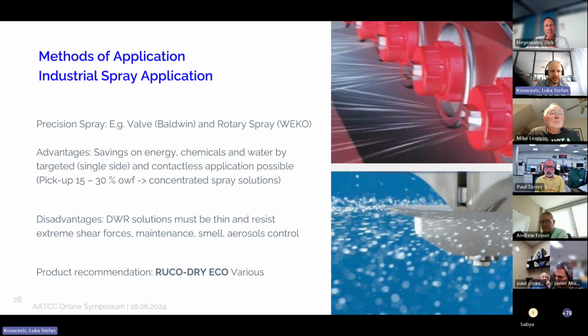So here you only have 15 to 30% pickup of the finishing lacquer compared to 60 to 80, or sometimes 50 to 80, on a regular pad application. So that means your spray solutions have to be a lot more concentrated. That also means you have less water in your spray solution, and in the end you have to evaporate less water from the finish after the finishing. That means you need to apply less energy. At the same time, these systems also create a lot less chemical waste, and what is also charming about this application technique is that with these spray applications, you can apply contactless, and you can also apply single-sided. Okay, so that means only at the side where you want the chemical to make effects.